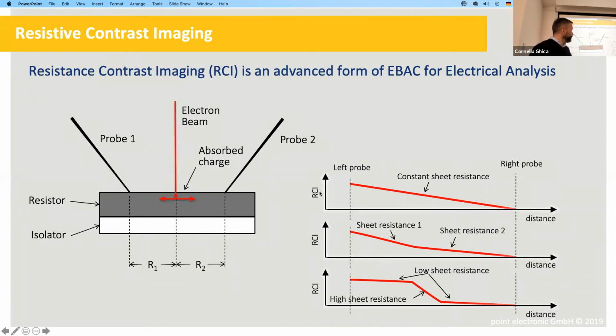So as we scan the probe from one side to the other, we will see the current going down. And if the material is uniform, we will see a constant gradient, so a constant decrease. If there are two grains, say, of different resistance, then we will see two different gradients. And from those, we can extract which one is higher, which one is lower, we can quantify resistance and so on. Most frequently it's used in a situation where we have a point of high resistance. So we have a low resistance, so the gradient is very small, then high resistance, where the gradient is very high, and another low resistance.